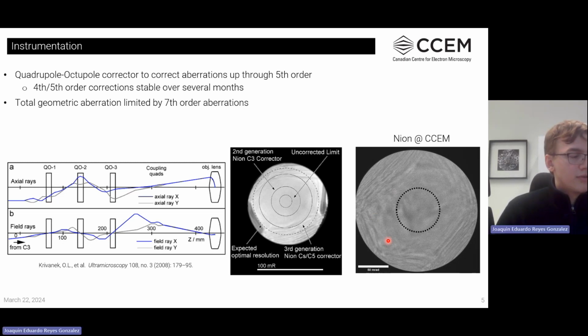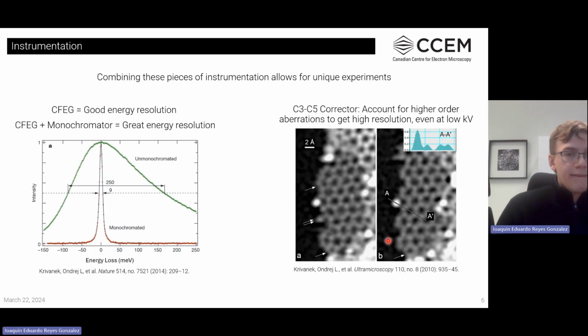And just to say what can we actually use all of this for? Well, the power of this isn't just the corrector. It's not just the monochromator. It's when we combine all of this together. If we have a CFEG, cold field emission gun, that's already great, it already gives great energy resolution. 250 millielectron volts would be very, very nice in a lot of instruments. But if you add the monochromator on top of it, you're getting very easily 10 or less millielectron volt energy resolution. You're already doing great.